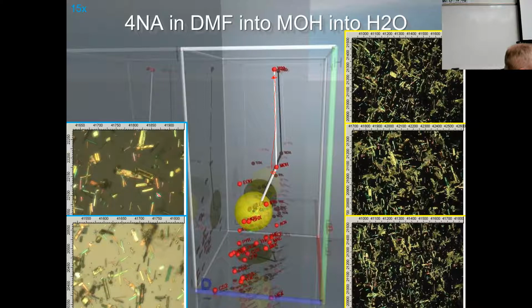They're pink and blue and yellow. I've got crossed polarizers here. And so I'm polarizing the light that's hitting the molecules from below, and then I've crossed the polarizers on my eyepiece and on the camera. So the crystals have to rotate light for it to get to my detector. And the different thicknesses of the crystals rotate light different degrees.